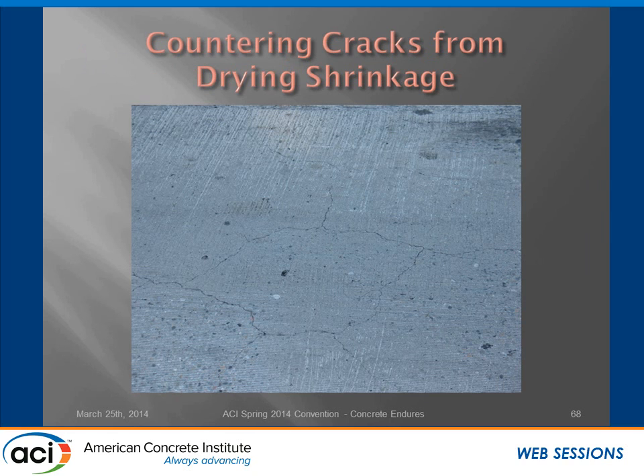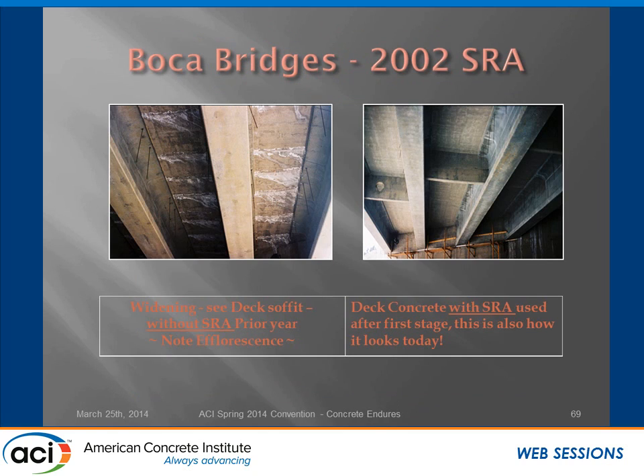How do you counter these drying shrinkage cracks? Well, Rick showed you this picture before. Around 2001, the picture on the left, stage construction, the same bridge, you can see the white stains there, that's water leaching through the cracks that are full depth. And that's only after about a year of being in service and being in stage construction. The next year they went over there, and that's when Rick said they decided to throw some shrinkage-reducing admixture in the mix. Same mix design, same contractor, different results.